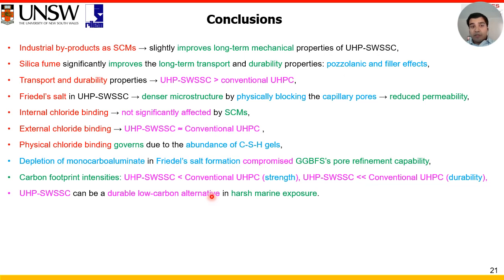So in conclusion, we can see that the industrial byproduct based SCMs can improve the mechanical properties slightly, but they can significantly enhance the transport and durability properties. Friedel's salt can densify the microstructure by partially blocking the capillary pores. Internal chloride binding is not significantly affected by the SCMs, and in terms of external chloride binding, the marine UHPC and conventional UHPC are very similar. Also, physical chloride binding seems to govern.